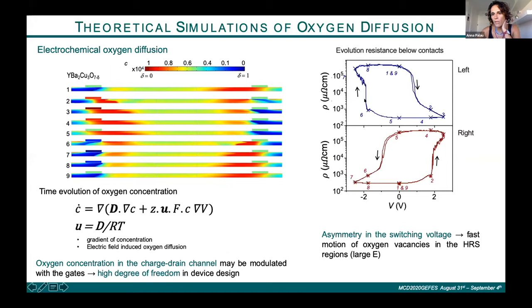Here, for example, we have the transition at 2, and here we have the transition at 1. And this is due to the fact that in the high resistance state, we have a very large electric field, and so this transition occurs much faster than the transition from the low to the high. So by changing, for example, the size of the contacts from one side to the other, or by trying to modulate what happens with different configurations of the contacts, we should be able to put these two very close, or as close as possible, to what you would need for the kinds of applications.